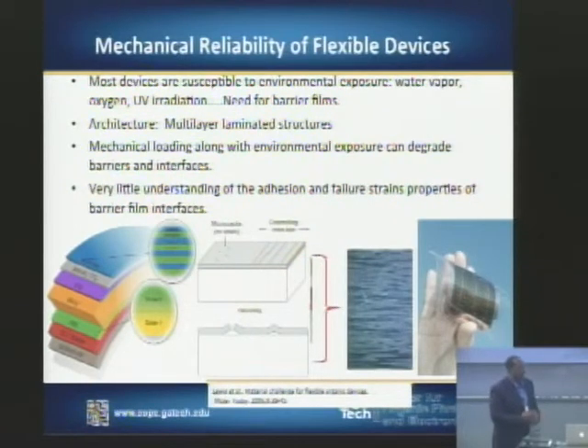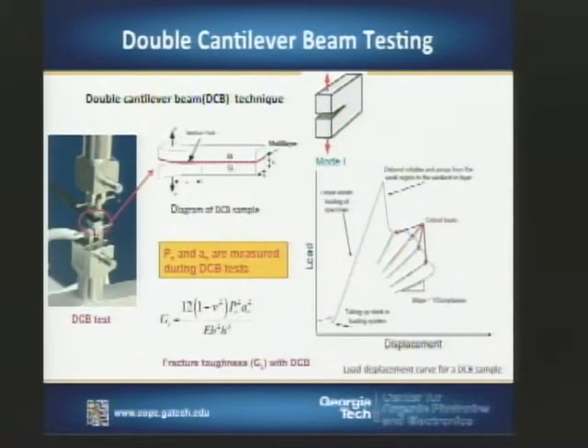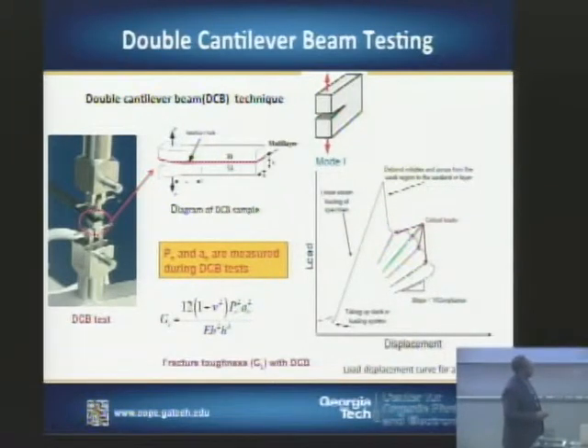In addition to that, we also want to understand the adhesion in the devices. Are there critical layers that will separate if we flex this or apply a certain amount of mechanical energy or strain to these particular interfaces? We do this using a mechanical test system where we place the device of interest between two silicon substrates, and we peel it apart using a double cantilever beam technique. To quantify this, we use the critical strain energy release rate. This basically says how much energy it takes to propagate a crack or to separate the particular interface we're looking at. And so we can quantify this.